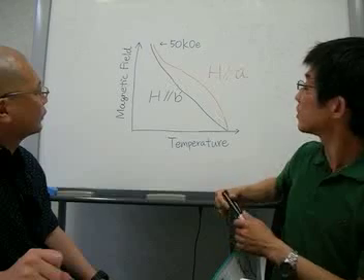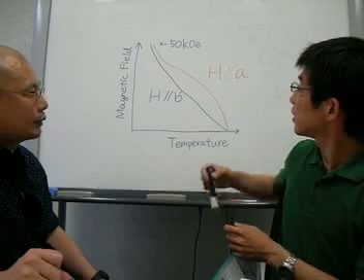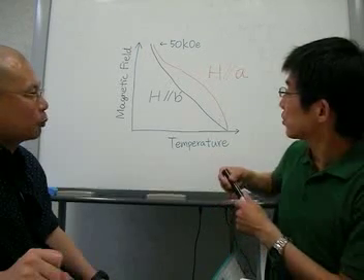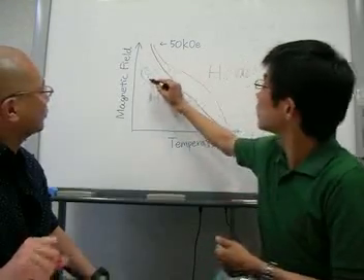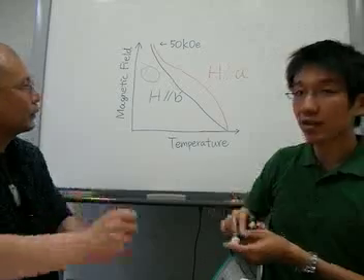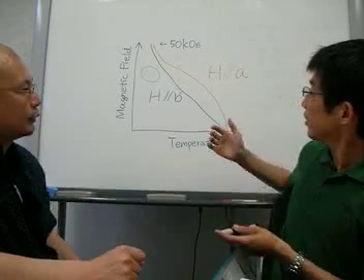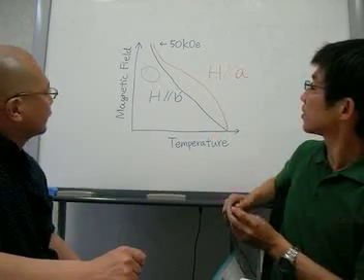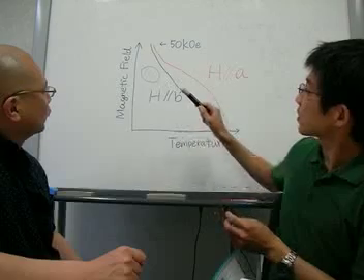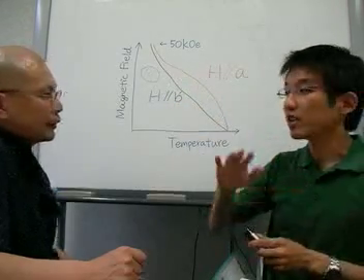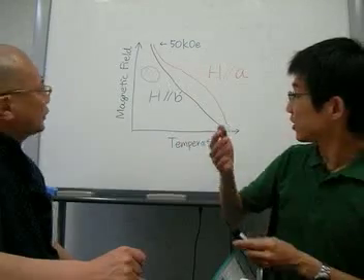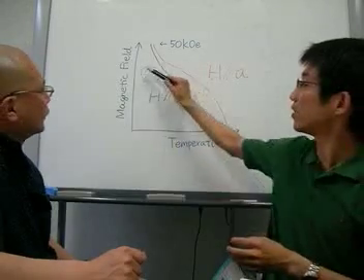So now we revealed that the border between superconducting state and the normal state is very different between this and this case. So our next goal is to reveal the inside of superconducting state. So in our scenario, some wavy or modulated superconductivity is realized in this high field region.